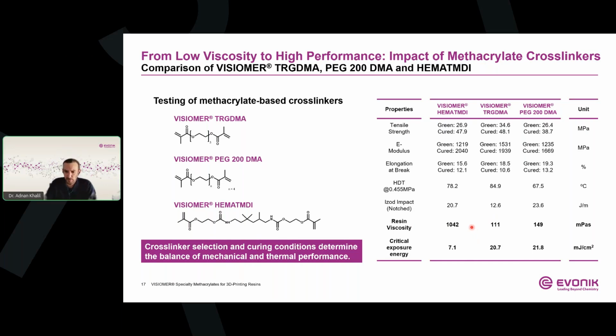So as we also saw previously, the HEMA TMDI delivers a unique combination of mechanical performance, toughness and thermal resistance, while the TRG DMA also delivers a high HDT in this comparison. It also exhibits a significantly lower impact resistance. The PEG 200 DMA, on the other hand, provides a better toughness, but at the expense of the thermal performance.